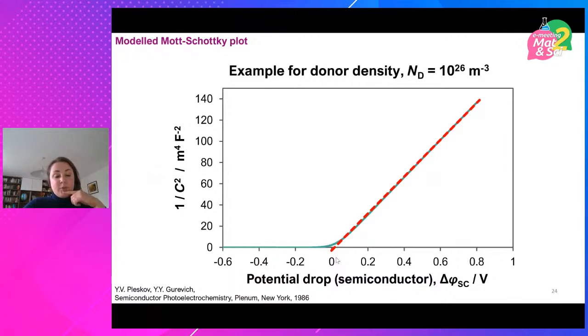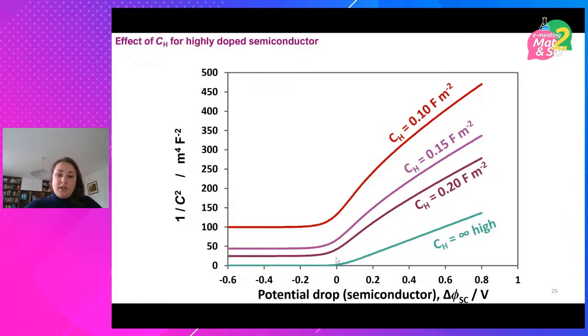But if you stop ignoring the capacitance of the Helmholtz layer and take some of the values that are being reported in the literature, depending on the actual value of the Helmholtz capacitance, the Mott-Schottky plots would look something like this. So the green one at the bottom is for when you assume that the capacitance is infinitely high and doesn't contribute.